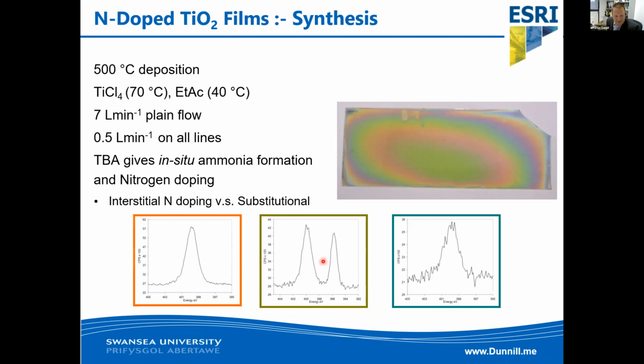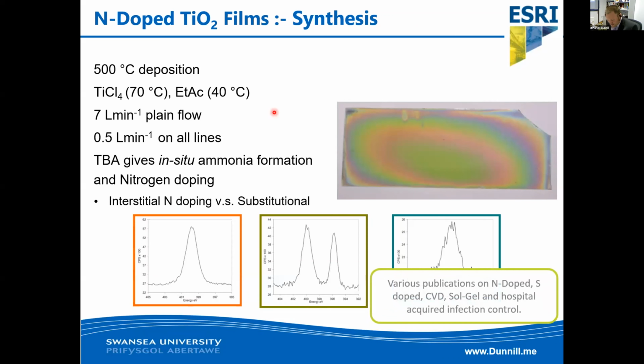There was a raging argument in the community as to whether it was substitutional that was best or whether it was interstitial that was best, and we were the first ones really to be able to make samples that had only substitutional and only interstitial, as well as samples that had both. And we really showed that the interstitial was the one that really made the difference in terms of the photocatalysis. So that was an interesting piece of work, and then we went on to show sulfur doped and various different types of solid state chemistry with CVD, sol gel, all looking at hospital acquired infection control.